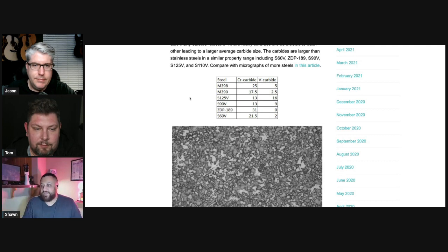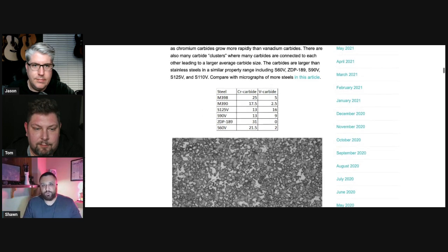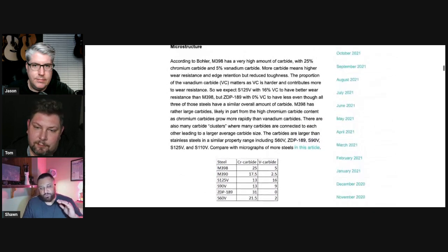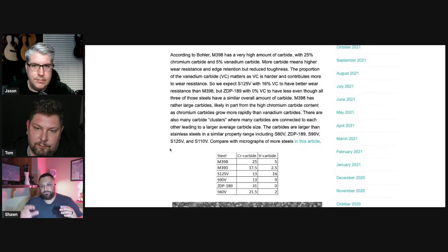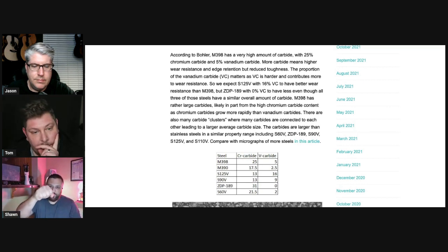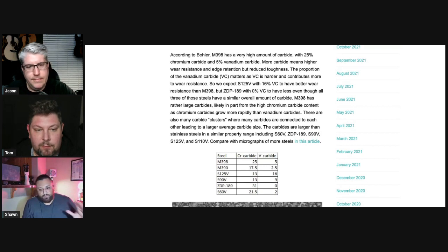And it has to do with the fact that vanadium is a much stronger carbide former. It wants to match up more with that carbon. So we have more of an equal balance between the vanadium and the carbon, which are forming more bonds. And when you think of these bonds that are being formed inside of the carbide, it's almost like springs. And so the more of these bonds that we have, the more of these elastic springs that we have. So when we're putting force on that carbide, it's more resistant. Versus when we get into the chromium carbides and sometimes some of the iron tungsten carbides, they're significantly softer.